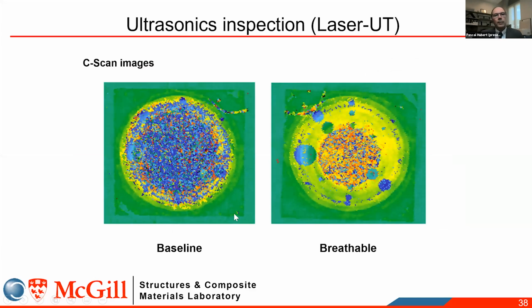So let's say you want to inspect the repair for looking at maybe kissing bonds, like weak bonds between the adhesive and the parent laminate. Well, if you have a lot of porosity at the bond line, you're just going to see this. On the left, you're going to see a lot of noise. You're not going to be able to pick these defects. With a clean, nice bond line, you're going to see those big circles that would be the kissing bonds. So those were artifacts that were placed in that bond line to see if you can detect them.